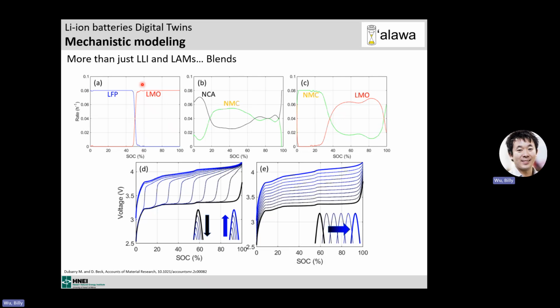But actually, both phases see more current because they see all the current at a time. So if you have a 50-50 blend, LFP and LMO are seeing twice the rate because all the current density is coming to one phase at a single time. But for overlapping or partially overlapping responses, the voltage variation and the current density are much more complex.